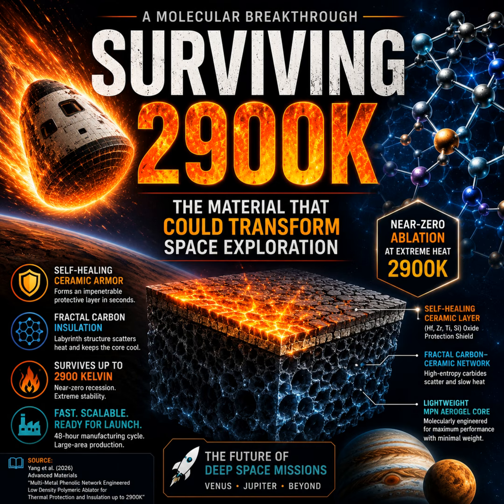Not at all. And for the insulation test, they exposed the material to 2500 Kelvin for 25 minutes. Almost half an hour of continuous thermal assault. Yep. And after all that, the backside of the shield experienced a thermal gradient of only 369 Kelvin. Wait, 369 Kelvin? That's less than 100 degrees Celsius. Barely boiling water temps on the inside, while the front face is dealing with blazing sun-level plasma. That is mind-blowing. The interior stays well within the operational temperature limits for basically any sensitive electronics. They completely shattered the density versus ablation trade-off. Yeah, they really did. By controlling the architecture at the atomic level, they achieved the ultra-light weight of a porous polymer, the thermal insulation of an aerogel, and the indestructible ablation resistance of a heavy ceramic all-in-one unified composite.